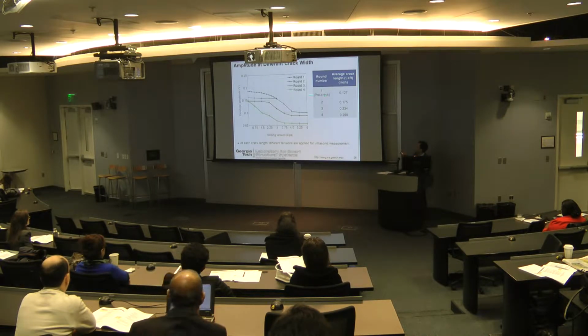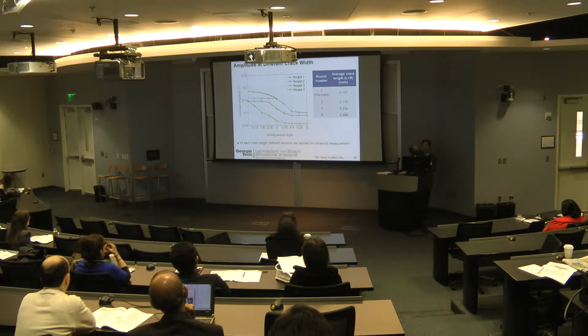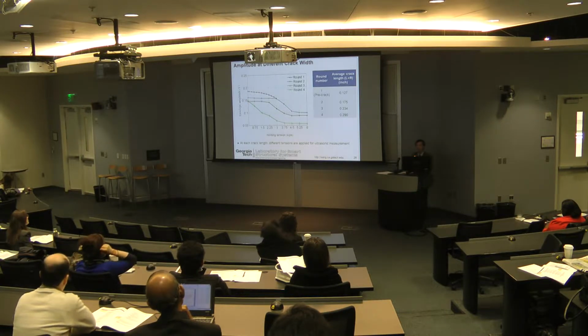After the 1,000 cycles, after round one, we stop at different tension levels. So we hold the specimen, we apply a constant tension, then do the ultrasonic excitation. We get the amplitude. So this is round one. And this is round two at different tension levels.